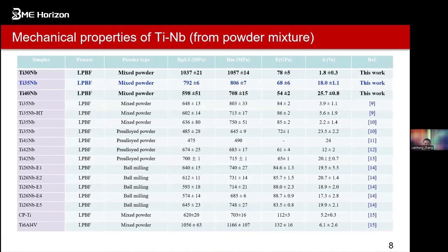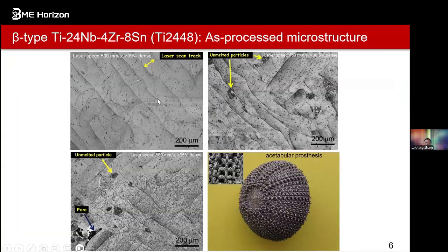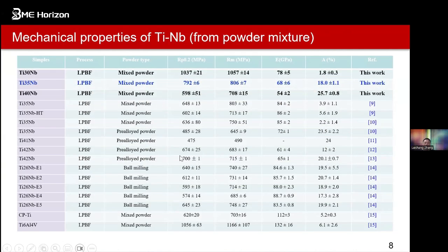Of course, we also produce a lot of titanium-niobium parts from powder mixing. This one was from pre-alloyed powders, but we can still produce a lot of parts from mixed powder. We try to make the parts cheaper. So we try mixing powders, and you can see the strength is very large, and the ductility is also large. We didn't do many, but the ductility is quite large compared to the traditional way. That will be very good. We can go to more than 20% ductility in these parts, produced at low cost from the pre-alloyed or powder mixture route.